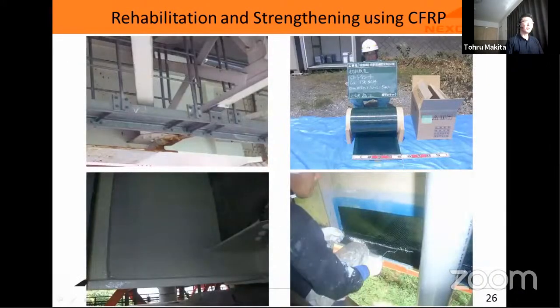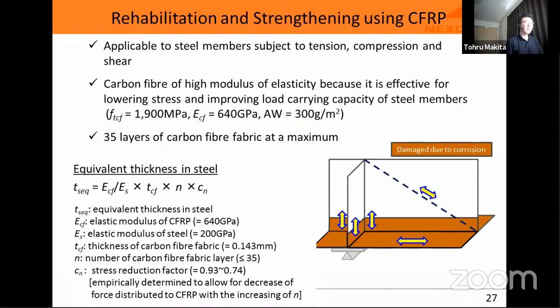So materials used in this method are light and one person is enough to undertake the intervention work. CFRP can be applied to steel members subject to tension, compression, and shear. High elastic modulus carbon fiber is used in the CFRP because it is effective for lowering stresses of steel members and improving load carrying capacity of steel members. You can apply 35 layers of carbon fiber fabric at a maximum. And after determining the steel member thickness to be recovered, the necessary number of carbon fiber fabric layers is calculated by using this equation.